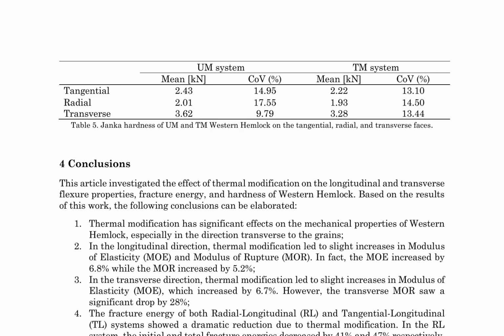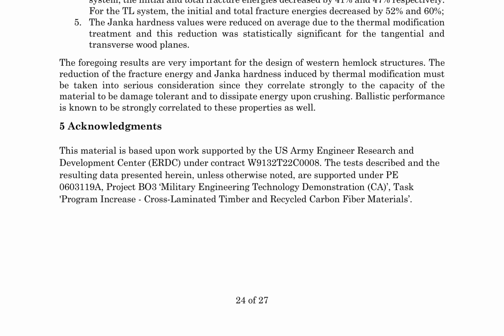1. Thermal modification has significant effects on the mechanical properties of Western hemlock, particularly in the direction transverse to the grain. 2. In the longitudinal direction, thermal modification leads to slight increases in modulus of elasticity, MOE, and modulus of rupture, MOR, with increases of 6.8% and 5.2%, respectively. 3. In the transverse direction, thermal modification leads to slight increases in MOE, with an increase of 6.7%, but a significant drop in MOR of 28%.